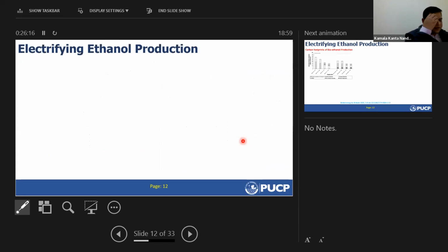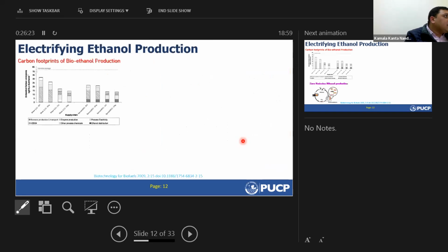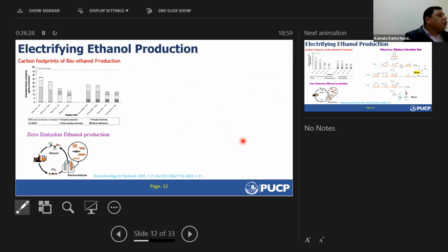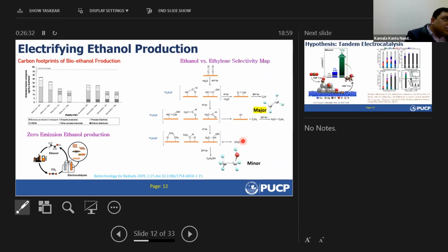Okay, then we were thinking about electrifying ethanol production, producing ethanol from CO2 by electrocatalysis, because bioethanol production still has some carbon footprint, and we wanted a zero-emission ethanol production. But the problem lies in the reaction mechanism. If you see the selectivity map, ethanol versus ethylene, lamentably they both proceed via a similar mechanism, and they only bifurcate at the last step, giving ethylene as the major product on copper and ethanol as the minor product.